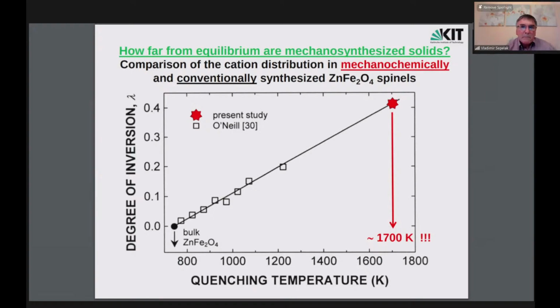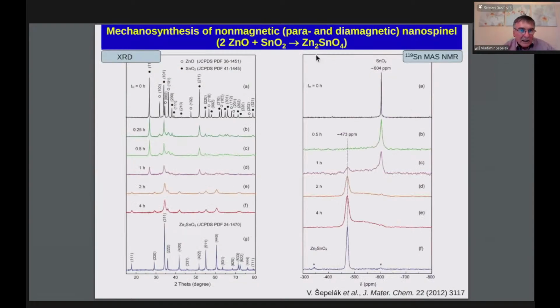And one example on the zinc stannate. Here is mechanosynthesis followed by X-ray diffraction, and here is the same progress of mechanosynthesis followed by magic angle spinning nuclear magnetic resonance spectroscopy. You see that within 4 hours of high energy ball milling, we obtain zinc stannate, starting now from zinc oxide